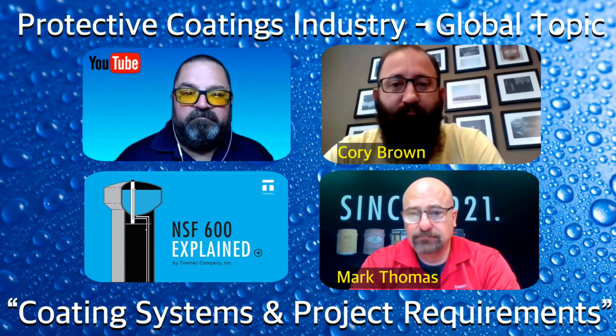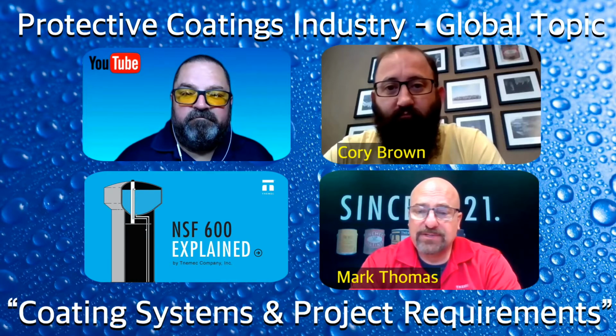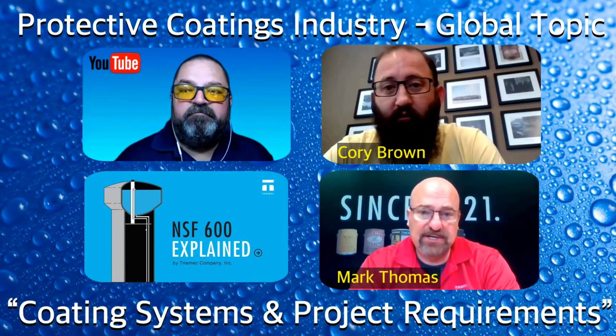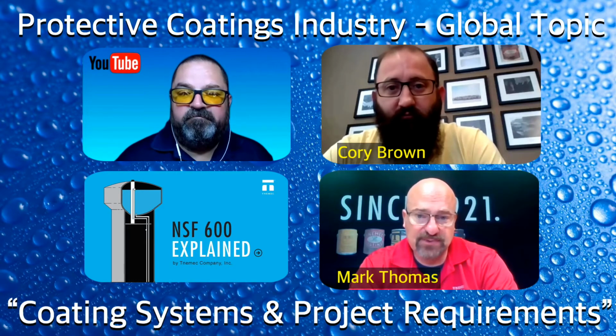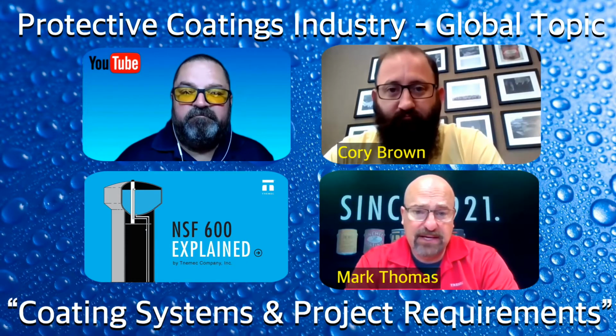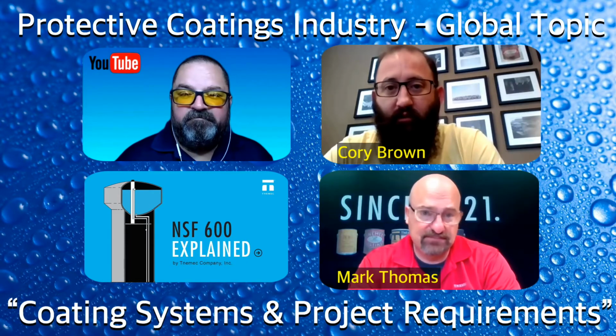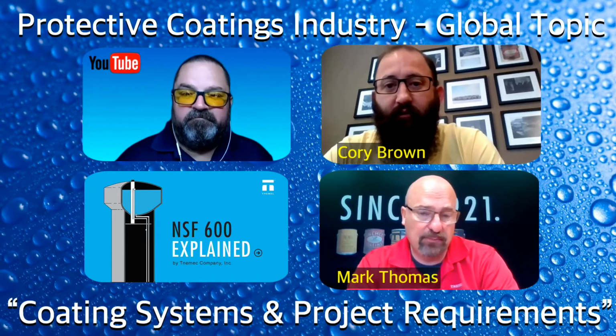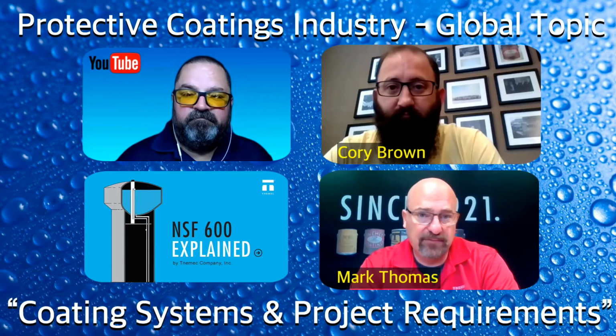And so specifiers will need to know to make note of that in their specifications and make that a requirement. And Corey, just to clarify too, that would be for direct application with those high solids materials. It does require that higher anchor profile. If you're using a zinc primer, that's generally going to be a lower anchor profile, but they'll just want to check those data sheets for the particular products, and depending if they're going direct with an epoxy or an aromatic urethane or going direct with the zinc first.